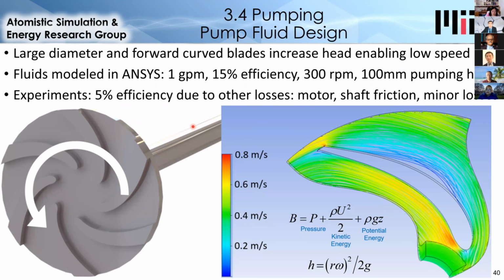So to design the pump, I used existing designs for centrifugal pumps, except for the initial experiment. To simplify it, I wanted to operate at low speed, a low RPM. And so I designed the pump with forward curved blades, whereas most centrifugal pumps use backward curved blades. The benefit here is that the fluid accelerates both radially and circumferentially, and this causes a greater pressure rise at a given pump speed. And so I modeled this pump in ANSYS and found that at 300 RPM, I would